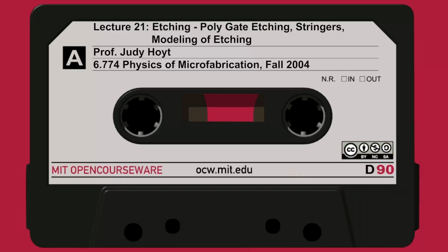This is an example of a wafer that's front-end processing only, so no metals are allowed to go into the tool, and you can get an etch rate of what's called the main etch. It's pretty fast. In fact, higher than you probably need in most etches today. The height of the poly today is probably only 1,000 angstroms, and this goes at 320 nanometers per minute. So quite efficient etching for poly gates, and can give you the kind of profile shape and selectivity that you need.